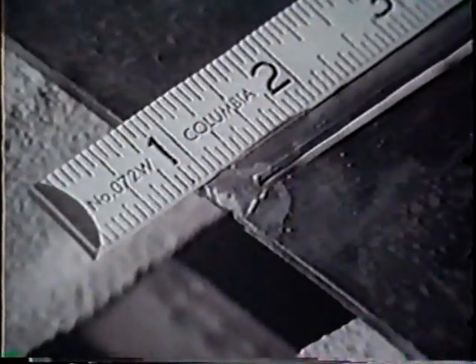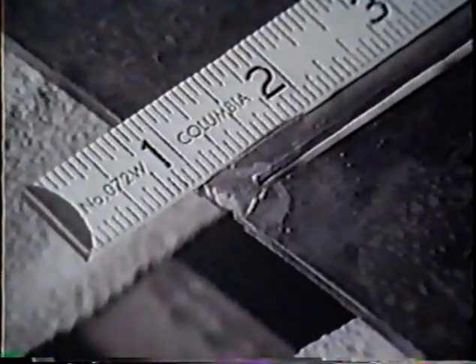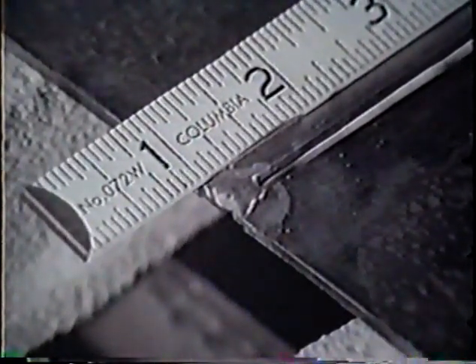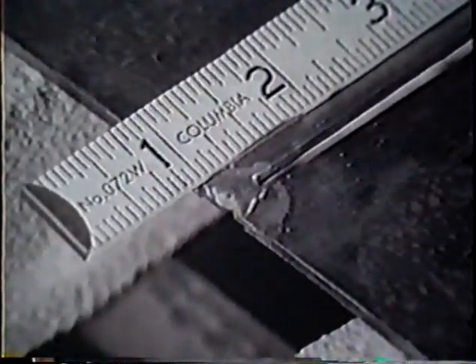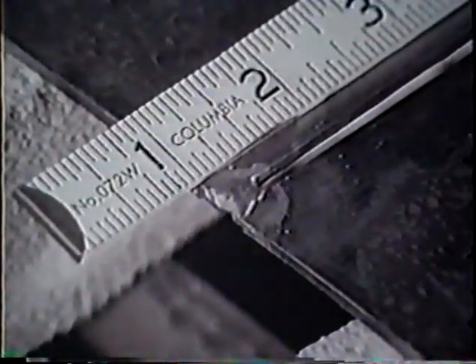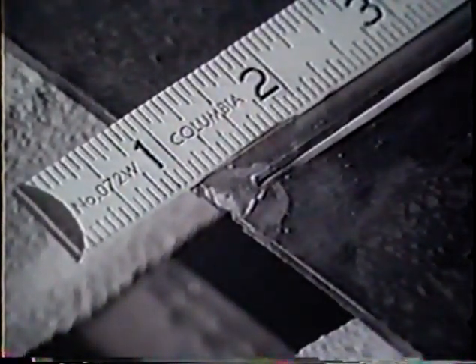The next step in the job is to tack the two pieces of metal together before the final weld is made. Good tack welds include the following 4 factors. First, they must be strong because they're part of the finished weld. Second, they should be approximately 1/4 to 1/2 inch in length. Third, they should be about 1/8 to 3/16 inch in width. And fourth, they should be made on the back side of the area to be welded, so they will not interfere with the finished weld.